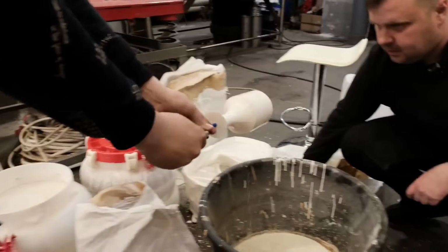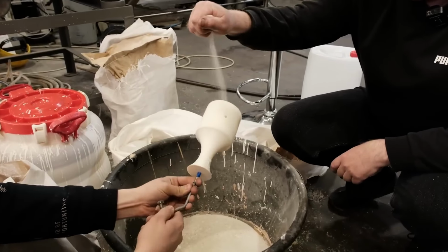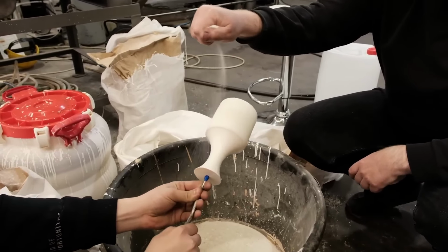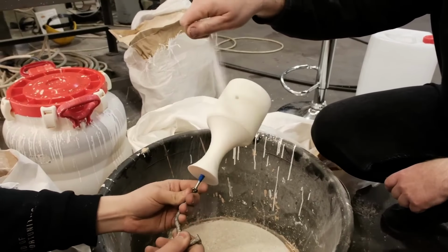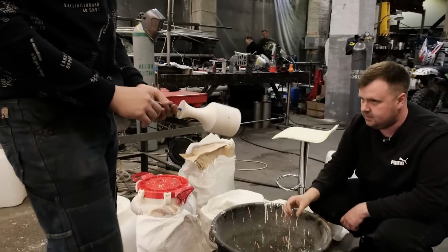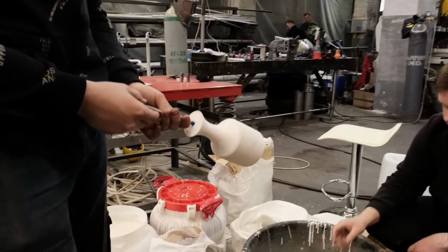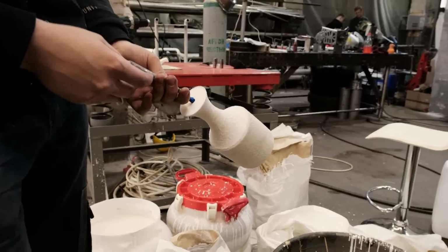After this step, the coated object is left to dry for about an hour, allowing the layer to harden and adhere properly. This process is repeated several times, usually applying between 5 and 8 layers in total to gradually build up the shell. Each layer is important for achieving the necessary thickness and strength.